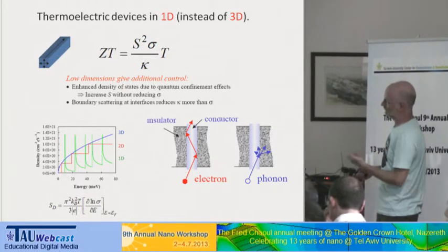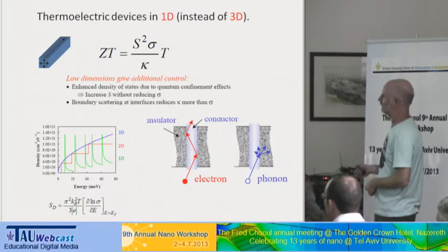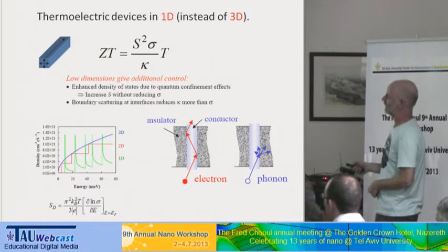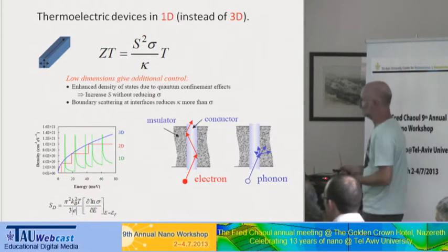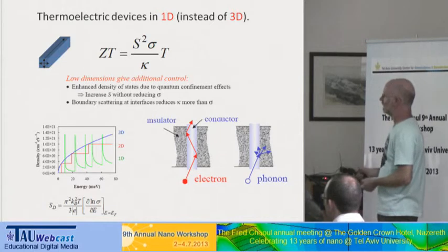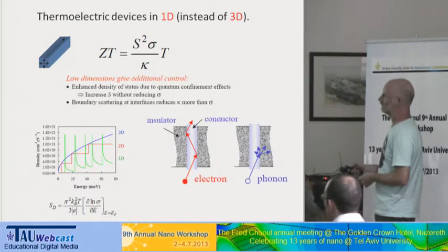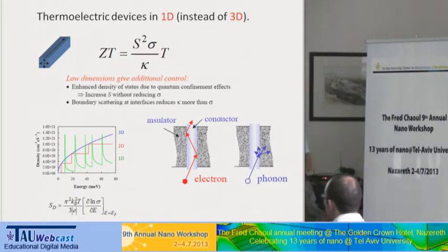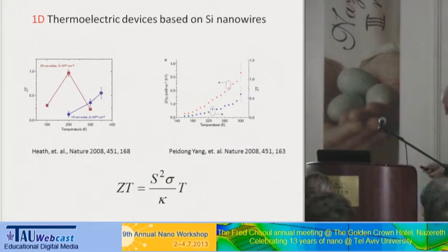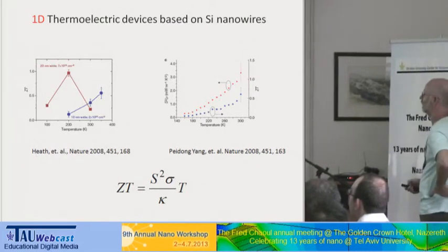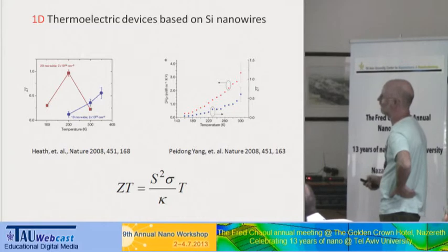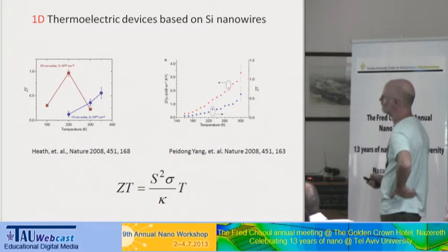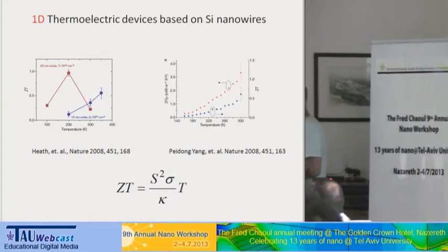The other thing is that people assume that the bouncing or the diffraction of the electrons on the boundaries of such a device won't interfere much with the electrical conductivity. So the effect on the sigma is going to be negligible. But then phonons are going to scatter on the boundaries, so the thermal conductivity is going to be low, and as a result, we expect to see high ZT materials. And here are two papers published a few years ago, back to back, by two quite respectable gentlemen, and they showed with silicon nanowires how they get ZT values in the order of 1 at room temperature, using wires with a diameter of 10 nanometers, 20 nanometers. So their conclusion in both cases was that they were actually affecting mainly the thermal conductivity.